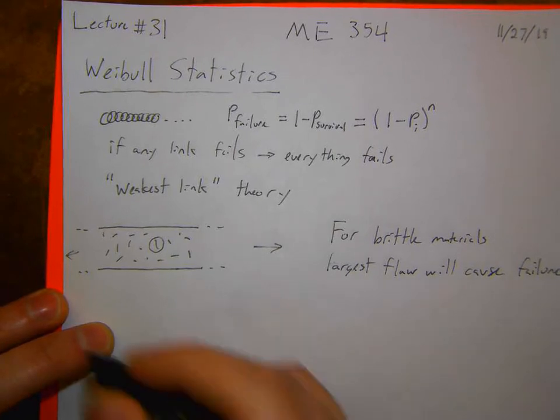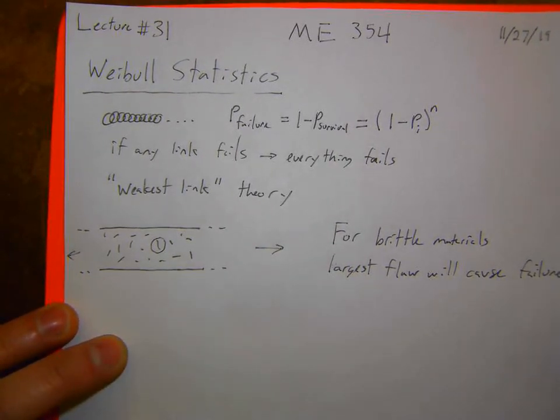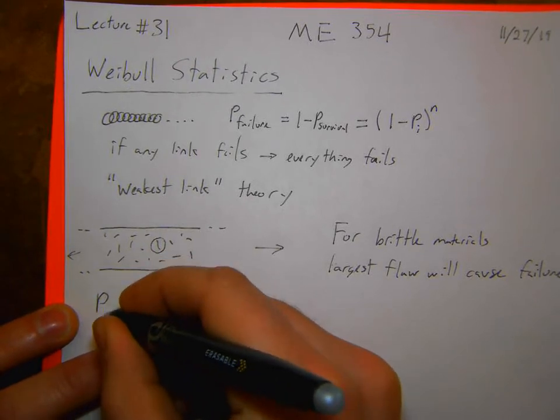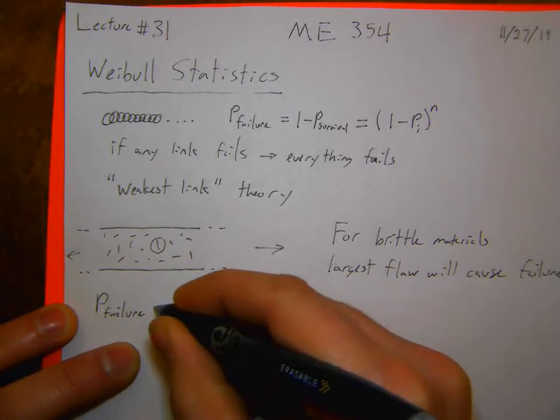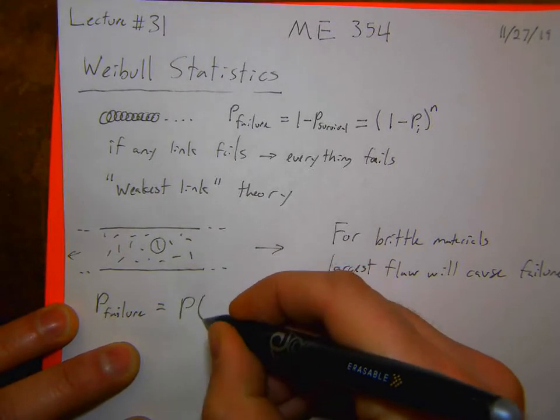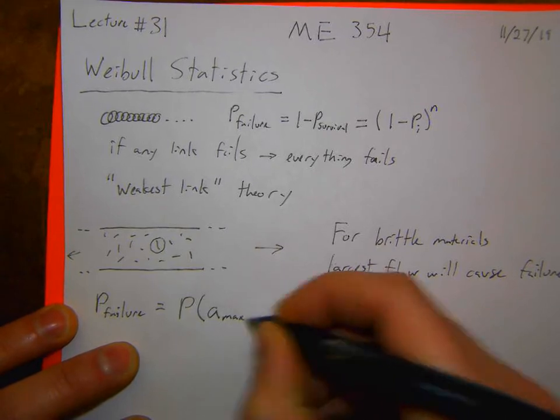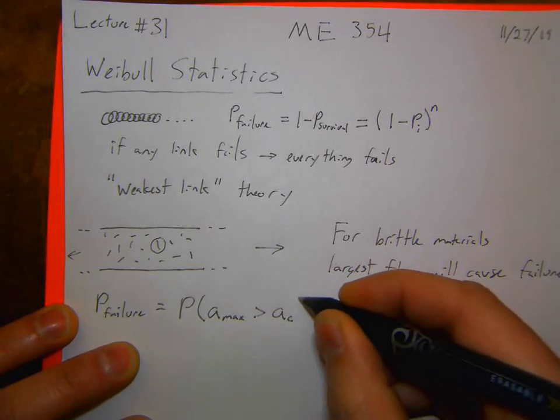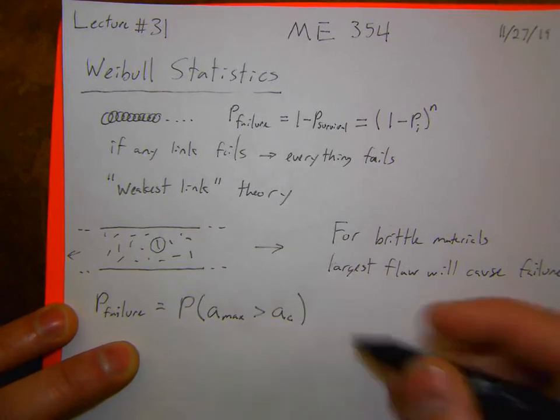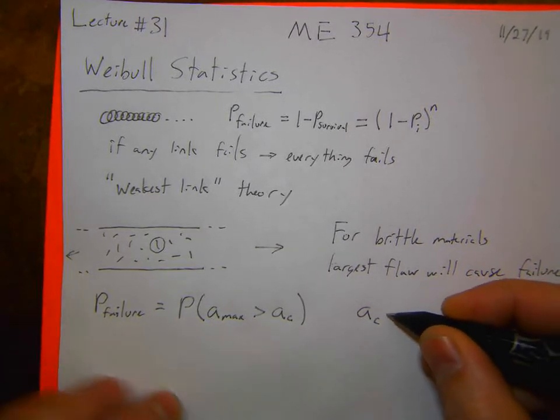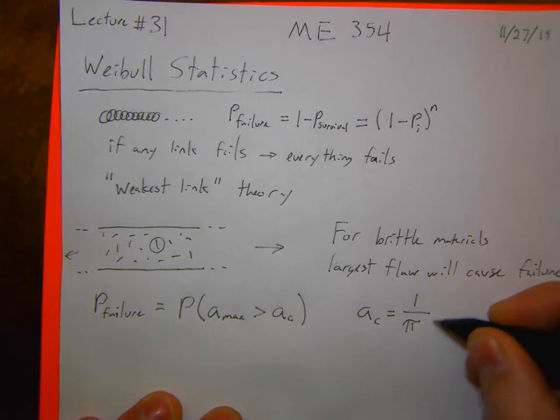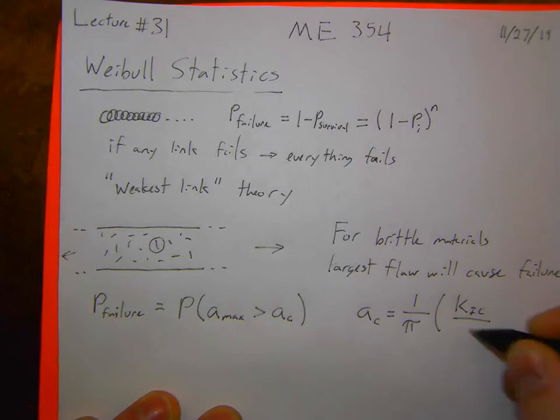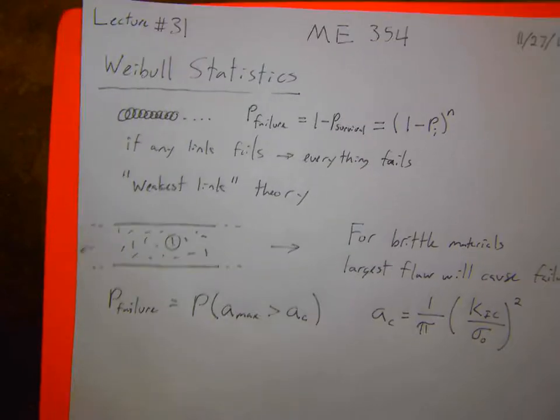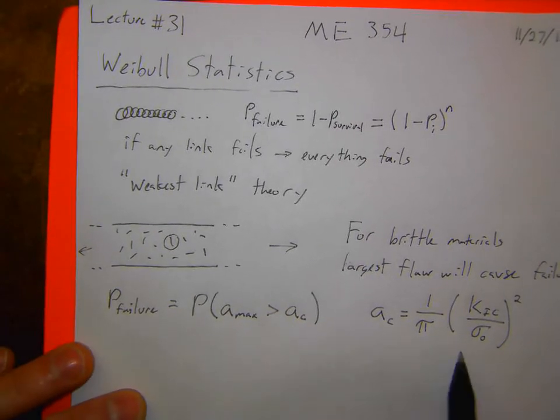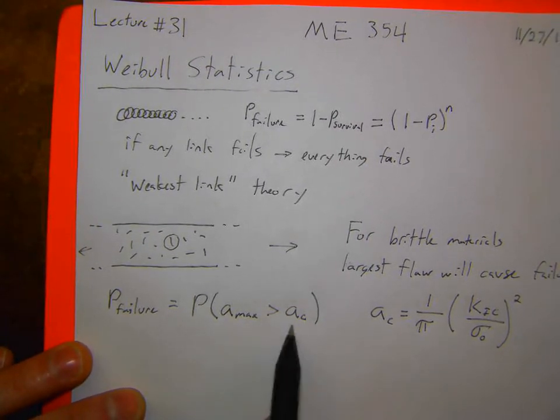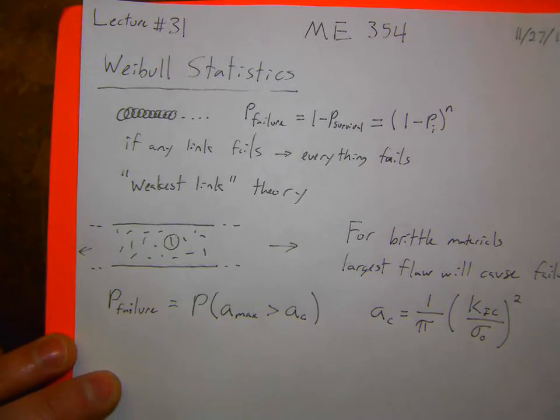So now I can say for this type of brittle material, the probability of failure is the probability, in terms of a crack, that I have some crack size larger than a critical crack. So the probability that the biggest crack is bigger than that critical crack size, which you remember hopefully from the last couple of days, is that the critical crack size is related to the fracture toughness, KIC, divided by the far field applied stress squared. So now this critical crack size depends on how much stress I'm applying to my material.